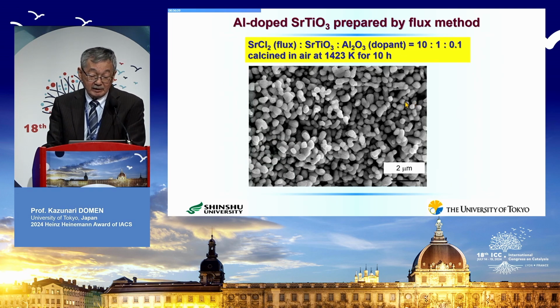Here I show the preparation procedure of this photocatalyst. After choosing a suitable strontium titanate, we then use a flux of strontium chloride and alumina, which is the dopant.